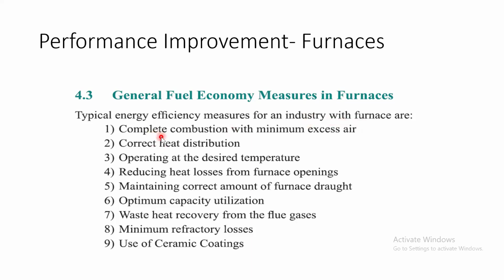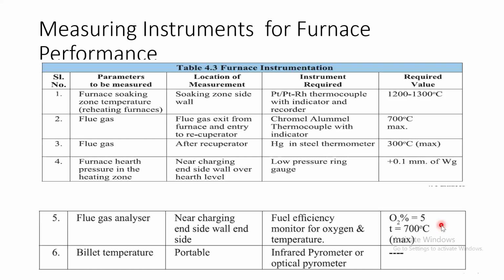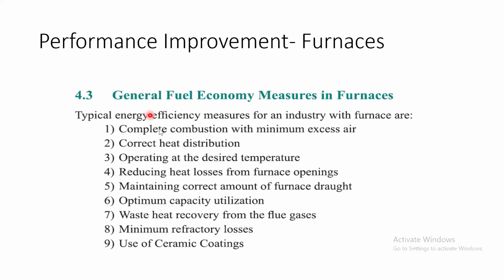So the first measure is complete combustion with minimum excess air. Already I told you that this O2% should be much less than 5, or around 3 to 5%. So that is the first measure you can take, complete combustion with minimum excess air. Second is uniform heat distribution or correct heat distribution. Then third is operating the furnace at the desired temperature. Then reducing heat losses from the furnace openings. Maintaining the correct amount of furnace draught.